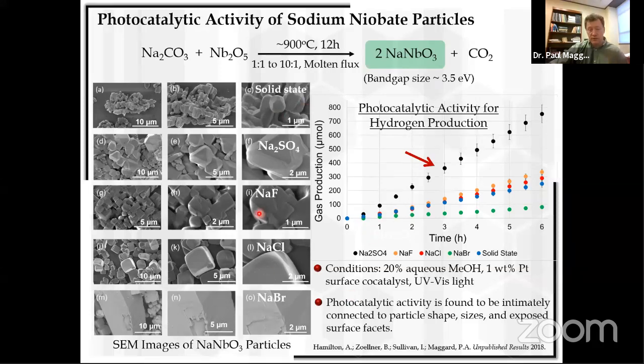So this is a very nice tuning that you can do synthetically, and then measure the photocatalytic activity for hydrogen production when you disperse these into a solution. So in this diagram on the right, what I've shown is the gas production, specifically molecular hydrogen versus time, for the products that we've obtained using the different fluxes. You can see the very highest activity is for when we have used the sodium sulfate flux to expose the 110 crystalline facets. Versus we have much lower activities for the sodium halide fluxes. And so this comes down to the point that it's not just particle size, but as well the surfaces that have a prominent effect many times in how active this material is right at the surface.